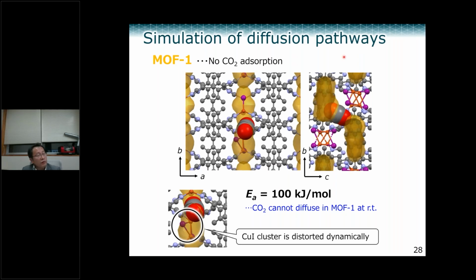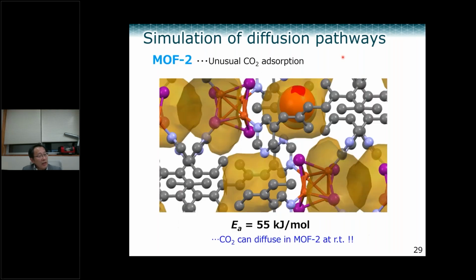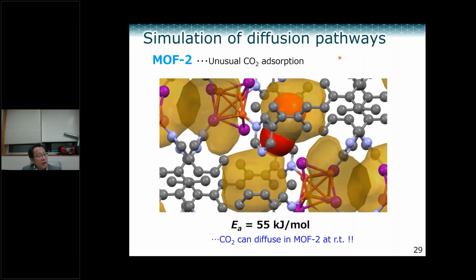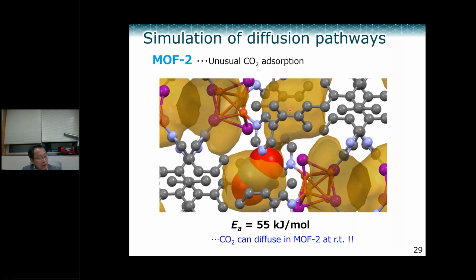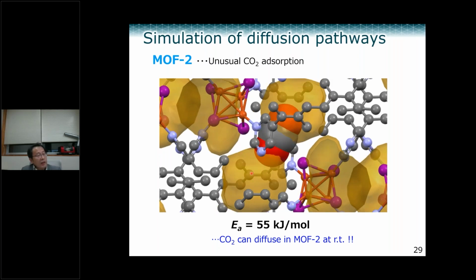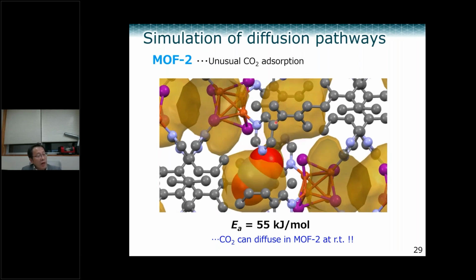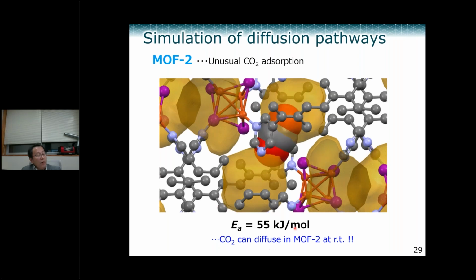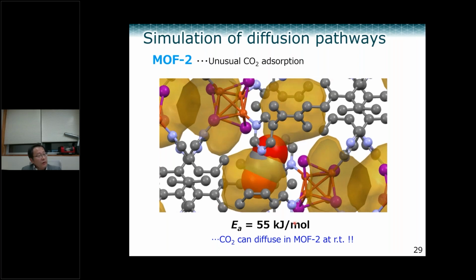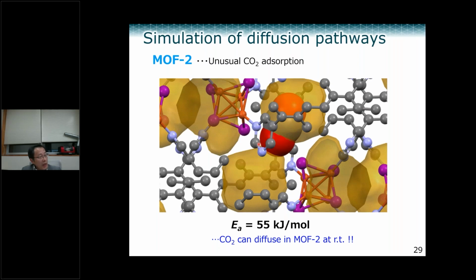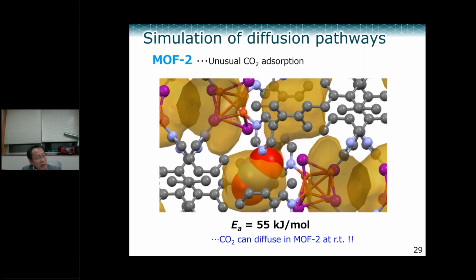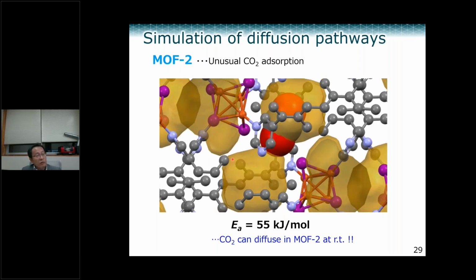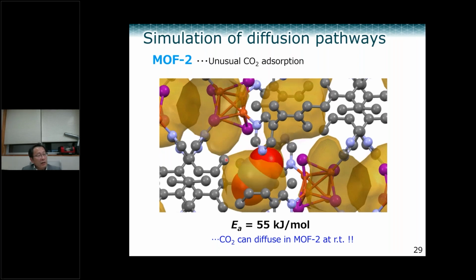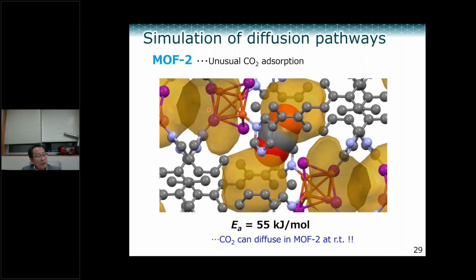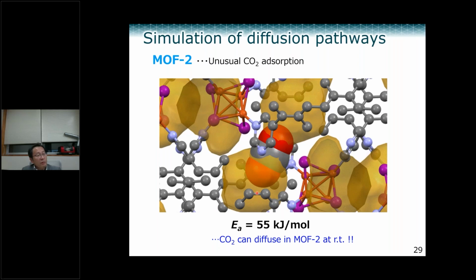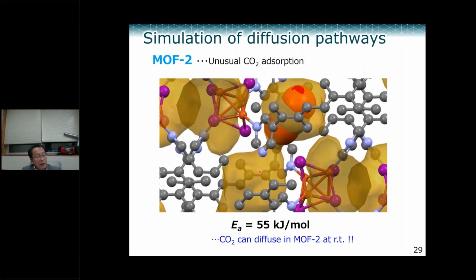So what about MOF2, the 3D MOF? In this case, you can see very smooth CO₂ movement from this point to the other. The activation energy is 55 kilojoule per mole, much lower than the MOF1 case, right? And we also calculated another pathway from this point to this point. In this case, the activation energy is over 80 kilojoule per mole. So you cannot expect any CO₂ movement from here to here. The only diffusion path is from this one to this one.